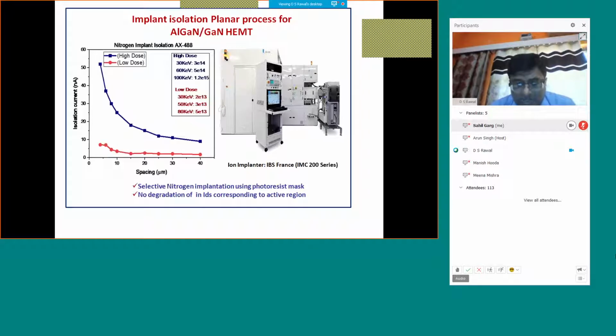Where you don't want implantation to take place, we cover that area with the mask using thick photoresist, and you have to choose your parameters such that after implantation you may be able to remove that photoresist easily. Otherwise this becomes very hard because of high heat generation, and the process becomes very difficult. So we have now this process, and we have our own ion implanter at SSPL, and we are using this planar process for this MESA isolation.